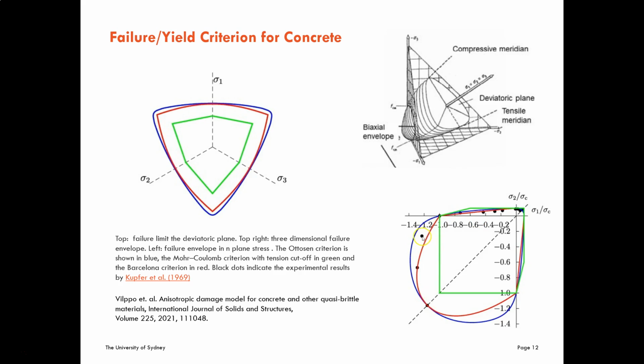So the black points correspond to the experimental data of Kupfer, and the green line corresponds to the Mohr-Coulomb criteria. And the other two curves correspond to the Ottosen or the Barcelona criteria. So you can see that the Mohr-Coulomb criteria doesn't reproduce the data very well, but it provides a conservative description of the failure of the concrete in different load paths. So in summary, if you are modeling steel, it is recommendable that you use the von Mises criteria, and if you are working with concrete, it's better that you use the Mohr-Coulomb criteria for conservative predictions of failure.